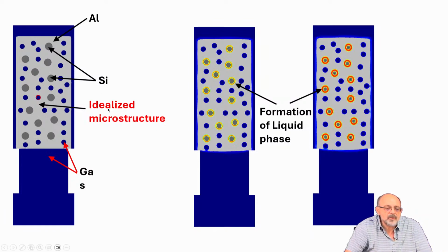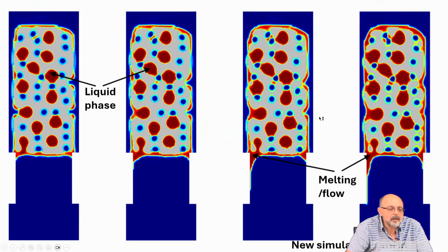So when we start melting, here's your liquid forming here, and then liquid grows. And some of those liquids percolate, and then you have capillary forces pulling down. See here. Others don't percolate. So this will not flow because it has not turned into granular material.